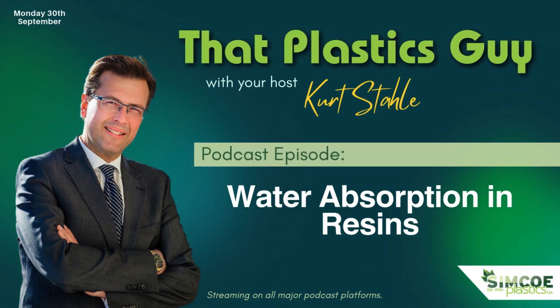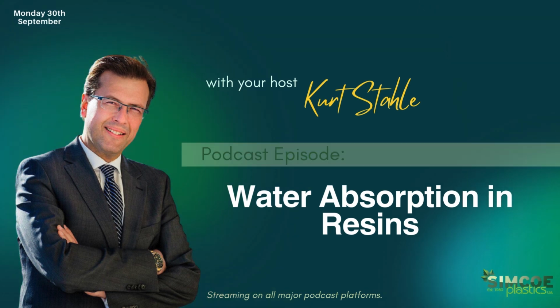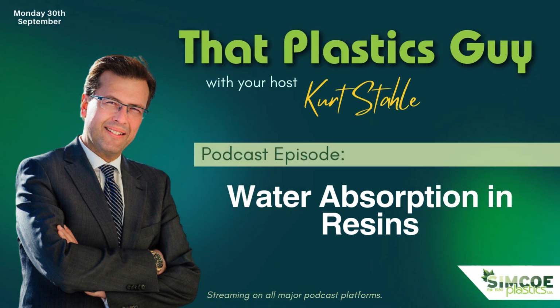I'm sure many of you who are in injection molding, and I'm sure that's most of you who are listening, if you've run nylon and you don't have much time in your shoot and ship environment, for example, you'll put freshly molded nylon parts into a Gaylord container lined with plastic, filled with water, and you anneal the parts. You're forcing that water uptake to shorten the time it takes to get the nylon part to reach its ideal physical properties. So some polymers have a natural tendency to absorb water, hygroscopic. Indeed, these superabsorbent polymers are gaining traction in advanced medical and construction applications.